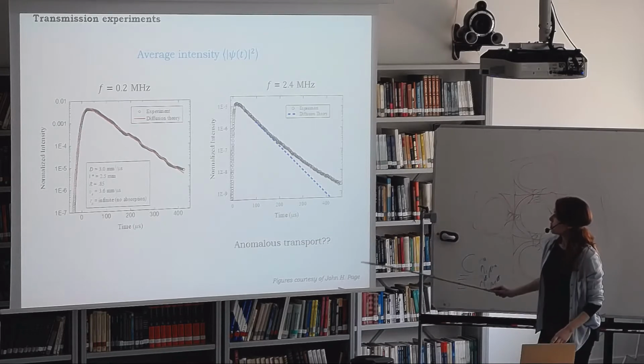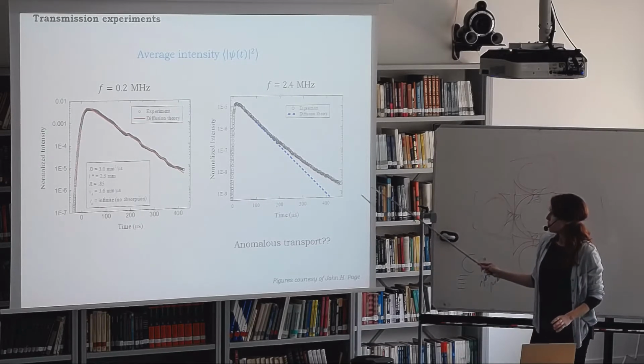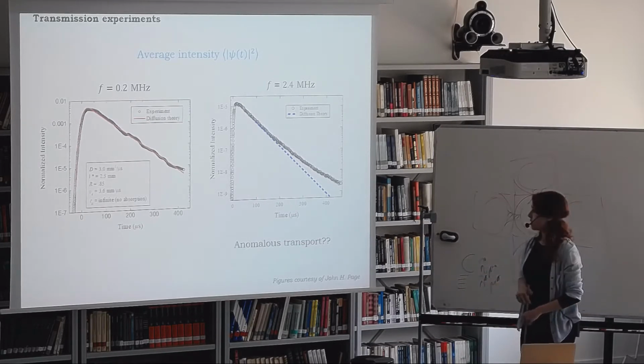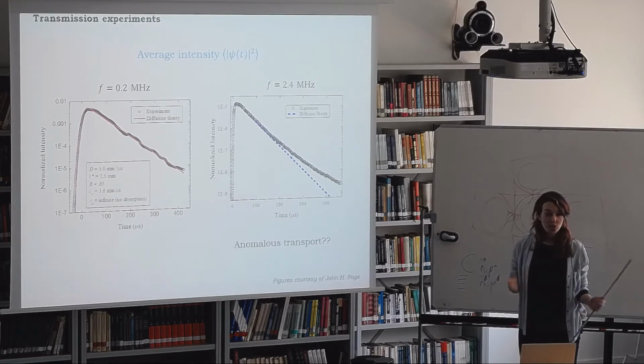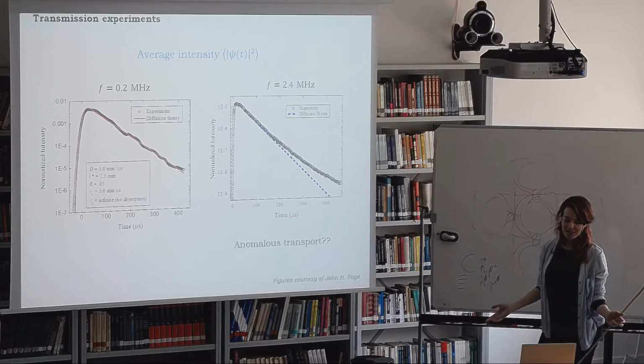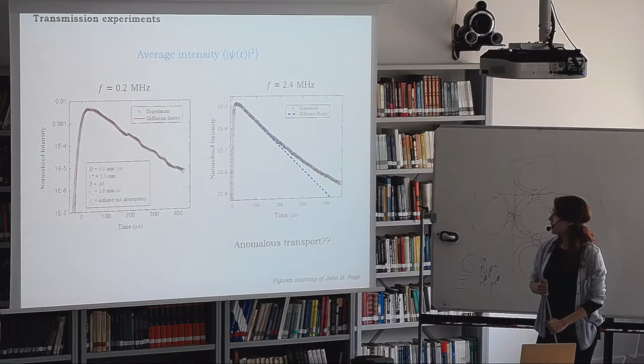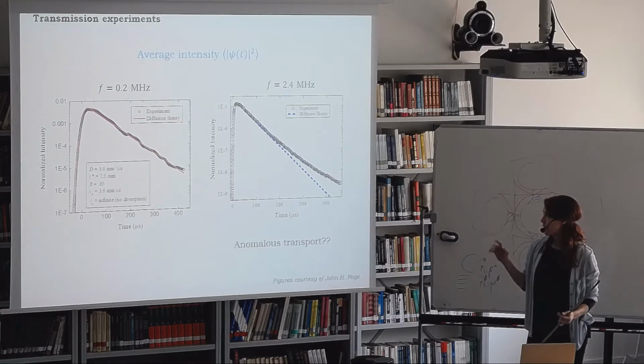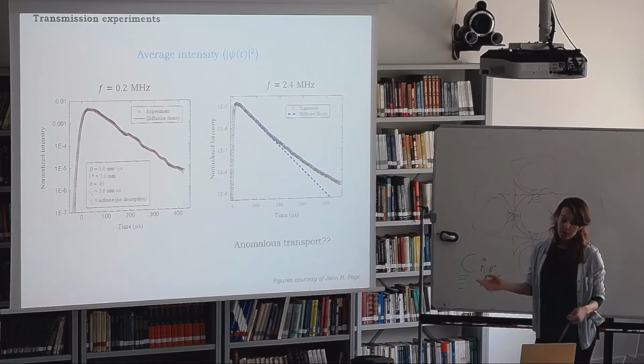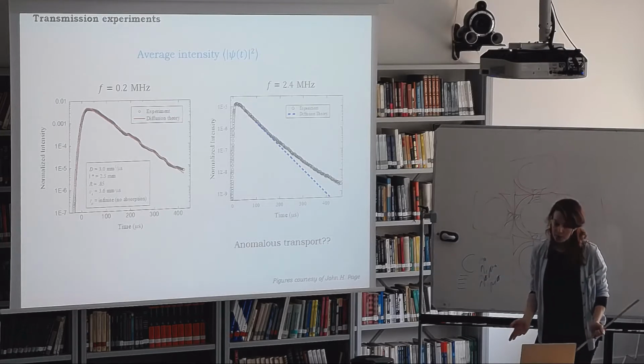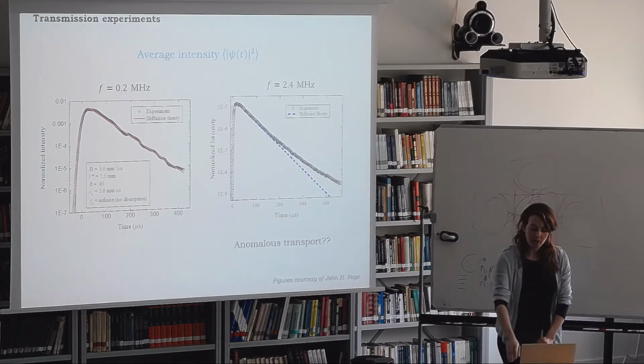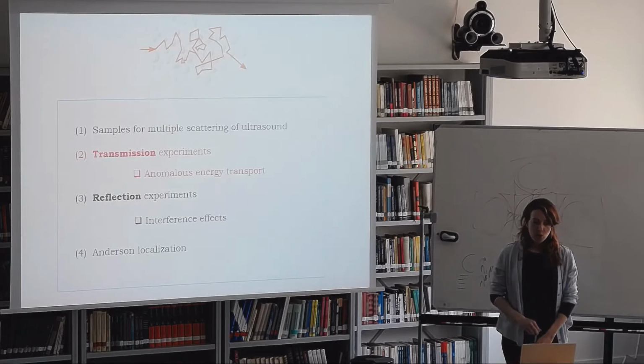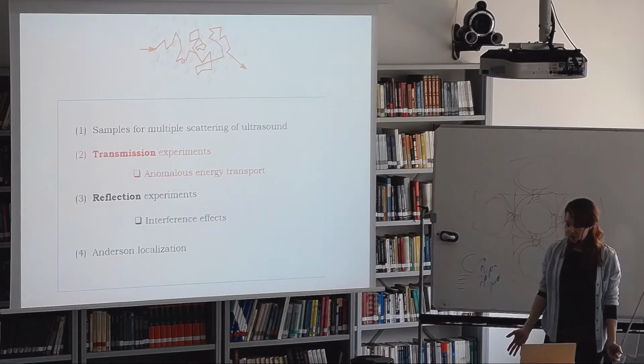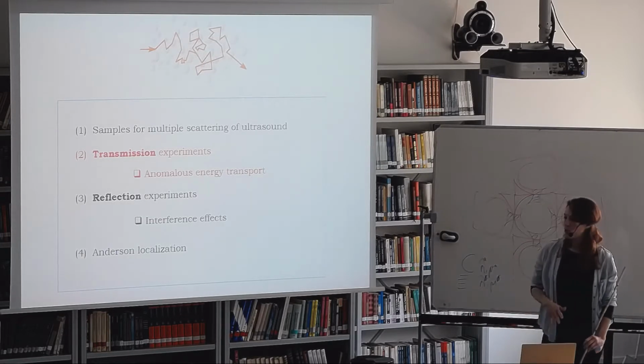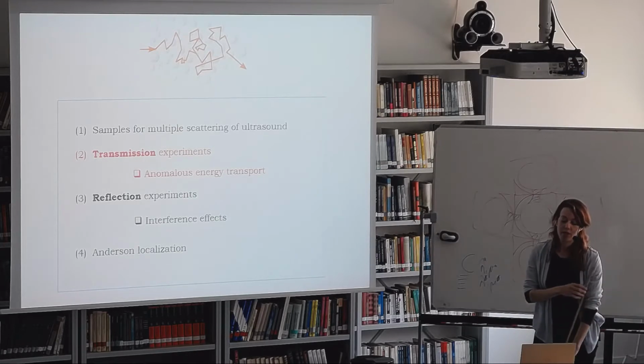But then for other frequencies, such as this one, diffusion theory does not fit the experiment. So this could be due to anomalous transport, which cannot be described by diffusion. But we need to be a little bit careful because there were lots of parameters involved in this fitting. We might have estimated absorption wrong, etc. So for this reason, we perform a little bit more advanced transmission experiments to have more unambiguous measurements of anomalous